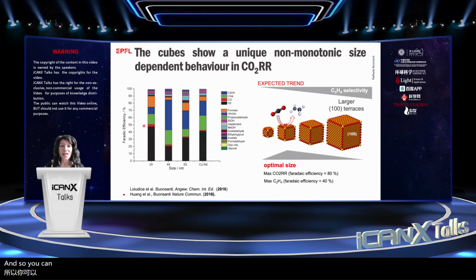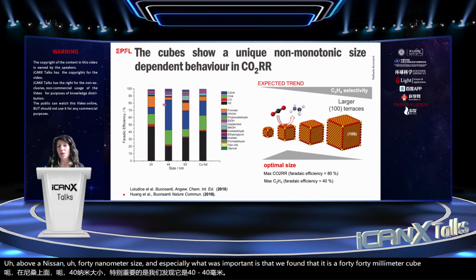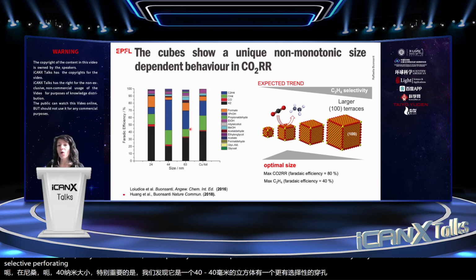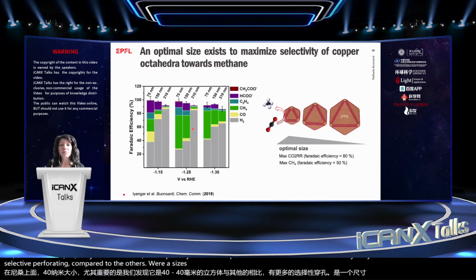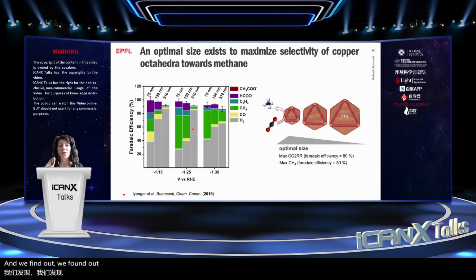And so you can see that compared to copper foil, the size of the cubes is actually important because it needs to be above this 40 nanometer size. And especially what was important is that we found that these 44 nanometer cubes were much more selective for ethylene compared to the other sizes. And we found also an interesting size-dependent selectivity in the case of the octahedra, with the 75 nanometer octahedra being much more selective for methane compared to the others.